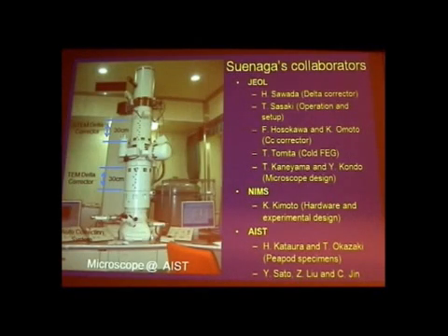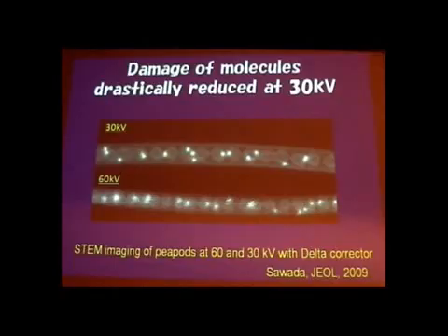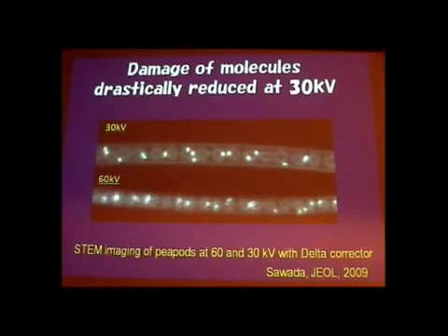Now the microscopy. These are the latest microscopes. There are three different ways to see individual atoms through modern microscopy. This is what's called dark field imaging, annular dark field imaging. Whereas in the previous one, the vacuum outside is always brighter than the inside. This contrast is reversed now. So brighter regions are where we have heavier atoms.